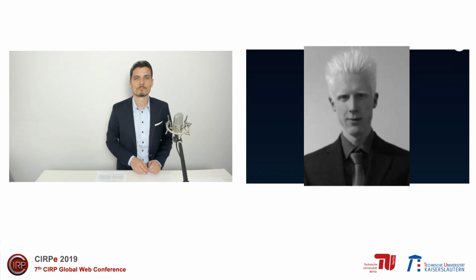By optimizing these parameters, and the result of that is what we used in this presentation, we can minimize the shear on the different lamina. We can minimize the voids in the resin, and also minimize the disalignment of the fibers. Although we can see that we still have some disalignment, so the problem is not completely fixed. But this is indeed one of the biggest drawbacks of the compression molding process.